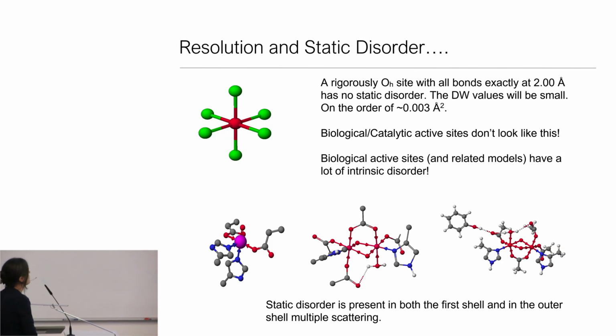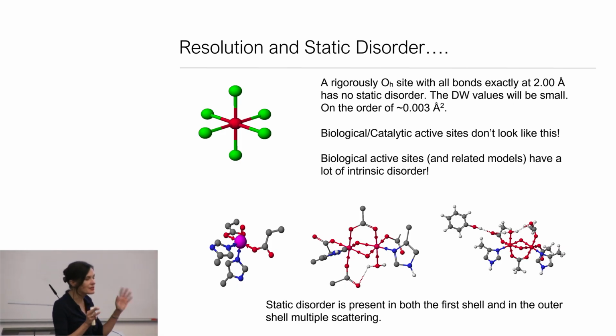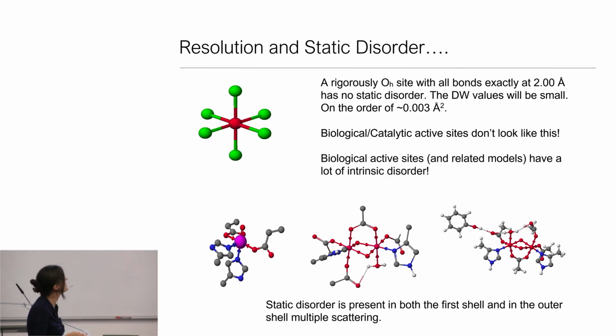Okay, good. So let's touch a little on static disorder and the Debye-Waller factor. When we teach, we often teach with these rigorously idealized structures like the octahedral site that we can have a character table and so on for. In a case like this, you're probably going to have all of these iron-chlorine vectors having basically the same exact distance. And at 2 angstroms, you're probably going to have a small Debye-Waller factor, something like 0.003 angstroms is a reasonable guess. So 0.001, 0.003, these are relatively well-ordered systems.